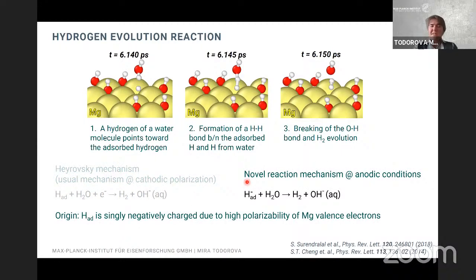What we propose is a modified reaction mechanism, which is based on the observation that the hydrogen atom at the surface is actually negatively charged. And this is a consequence of the high polarizability of the magnesium valence electrons, which lead also in other cases to somewhat peculiar behavior of magnesium. And in this way, the hydrogen itself can provide the electron for this reaction.